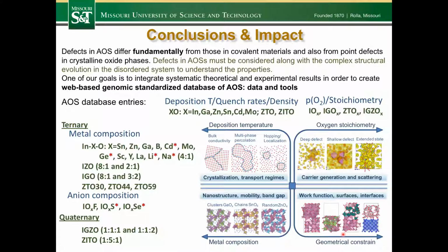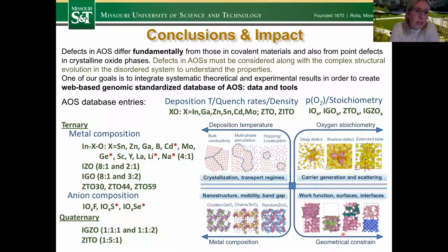I hope that I was able to show that defects in amorphous oxides differ fundamentally from those in covalent materials and also from point defects in the crystalline oxides. We must consider these defects along with the evolution in the disordered structure. To understand the properties, we cannot do it separately. We have to combine and look at the medium and long range ordering as well.